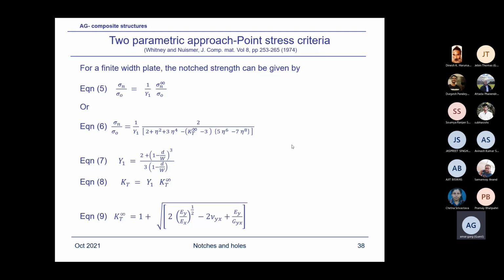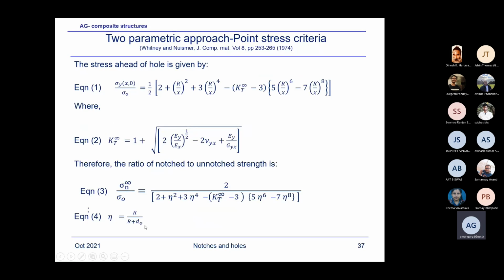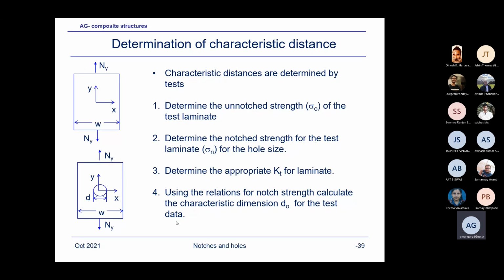So there are two unknowns over here, as you can see. One is sigma naught, which is the unnotched strength, and depends upon the laminate type, layup, material. Then there is another parameter, eta, which is basically a function of d naught. So there are two parameters, sigma naught and d naught. And both of these parameters depend upon the material, and various other parameters are shown in the table, which determine how you then characterize these parameters. You have to determine by test the values of sigma naught and d naught using the notched coupons and unnotched coupons.